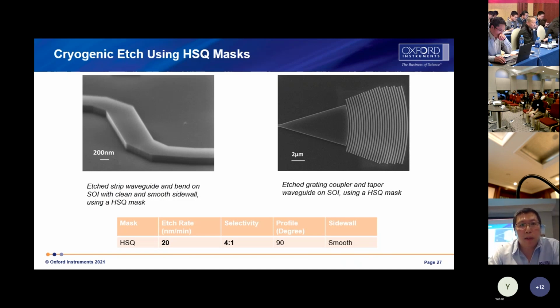Using an HSQ mask, we're using RIE mode cryo etching. We achieved higher selectivity, 4 to 1. The selectivity 4 to 1 is high because the etching rate is very low. It's down to 20 nanometer per minute.